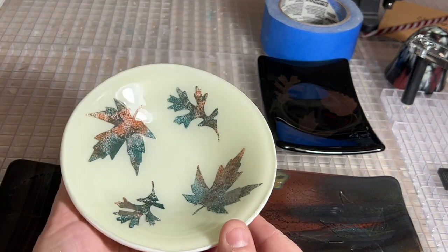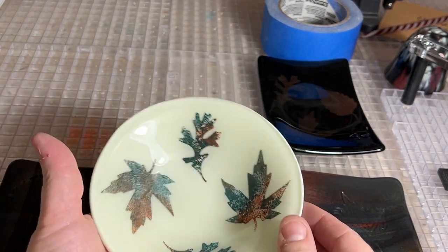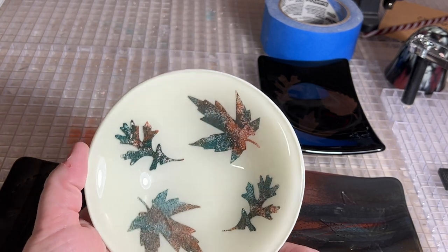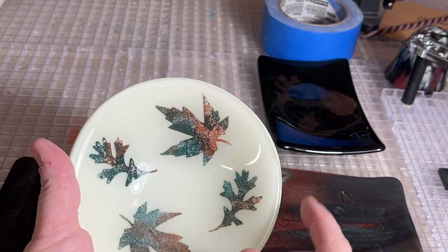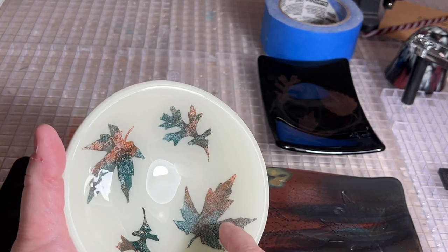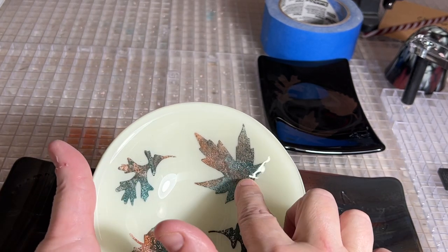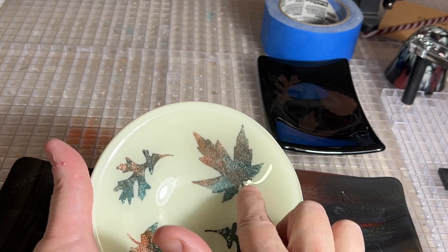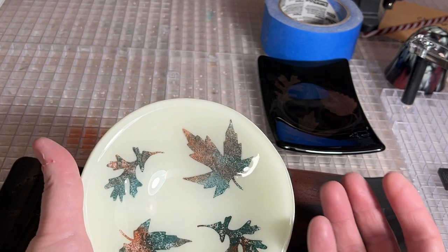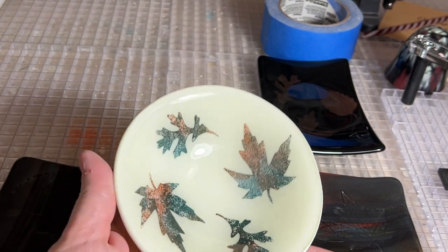I used glass line paint on thin fire and papyrus, and really there's no difference. The only difference is just in my application of paint. I didn't get it quite as densely covered, and this one seems a little paler, and again, I think it was just my paint coverage. These two were the thin fire, though, so it could be that because that's a little bit thinner material, it pulled into the glass, and that could be why we lost a little bit of color there.